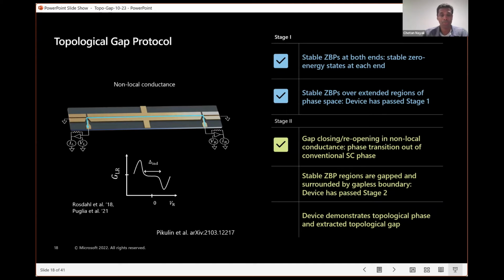And then we put these things together. We check to see if there are regions with stable zero bias peaks that are gapped, but the boundary of those regions is gapless. And if that's the case, the device is past stage 2. The device demonstrates the topological phase, and we extract the topological gap.